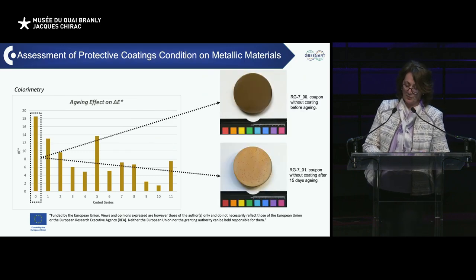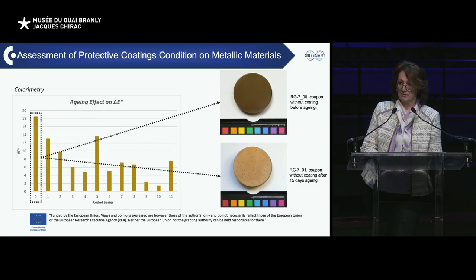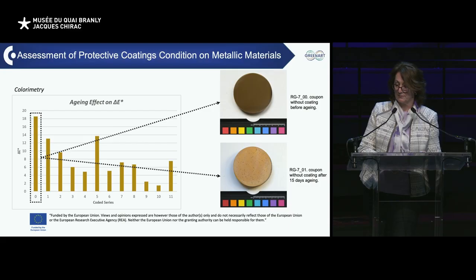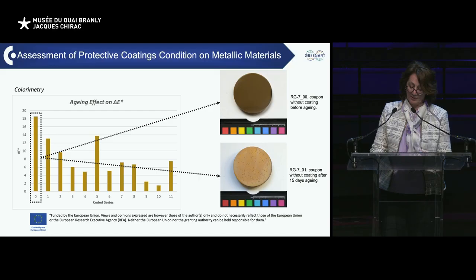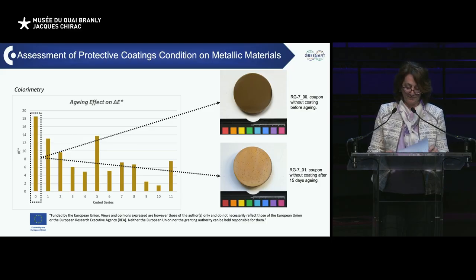Take, for instance, our code 0 sample, the uncoated metallic bronze. Its delta E value is remarkably high. And if you look at the comparative photos, you'll see that what we observed visually aligns perfectly with the colorimetric data. The whiter hue I mentioned earlier is evident in the photo on the bottom right. Now we also notice some localized stain-like features. These appear to be related to microstructure reactions between the metallic bronze and its environment, a case that is currently studied in our team via microscopy and microanalysis techniques, optical microscopy and SEM-EDS, actually.